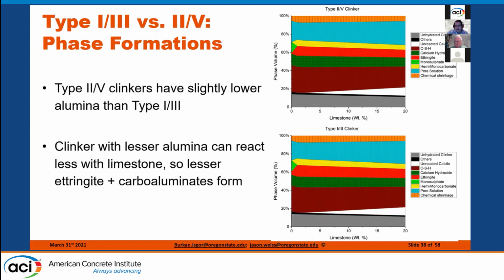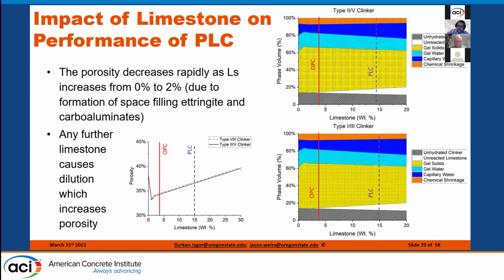Now, if we compare the type 1.3 shown on the bottom clinker and the 2.5 shown here on the top, what we notice is the plots look incredibly similar. Even though the clinker has slightly less alumina, this is really overblown in a lot of these discussions, and there's not a huge difference in the way these two clinkers behave. If we now look at the overall porosity in these systems, the type 1.3 is shown here in red and the type 2.5 is shown here in black. Even though there are slight differences in the clinker used to make these materials, they're very, very similar in terms of their overall porosity and the overall reactions that we're going to get in these systems.